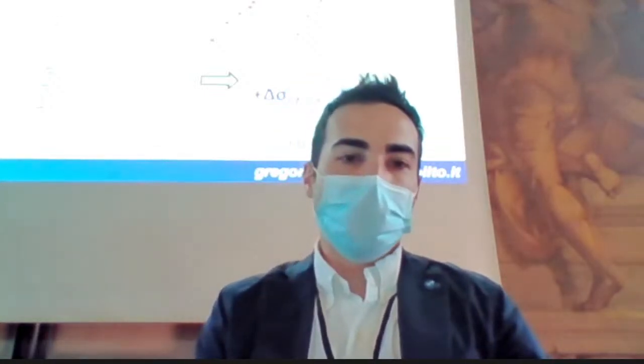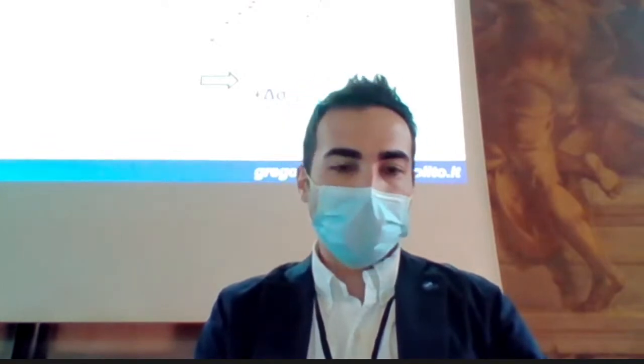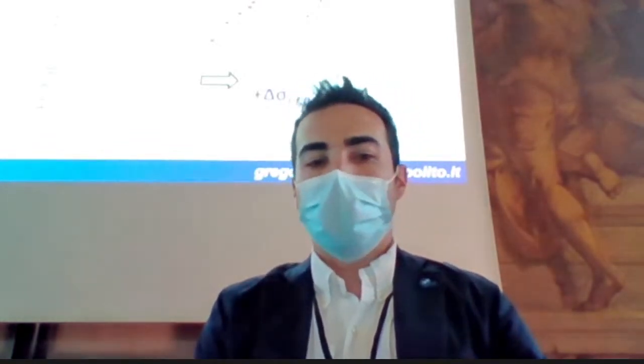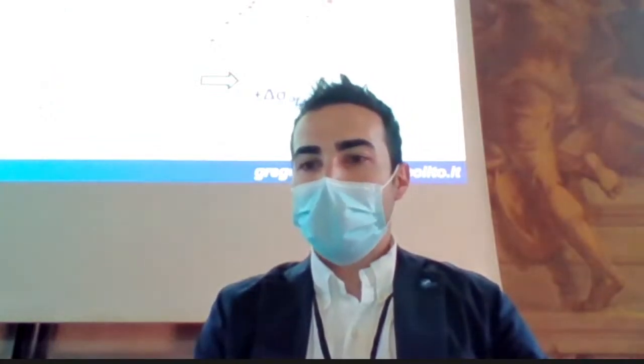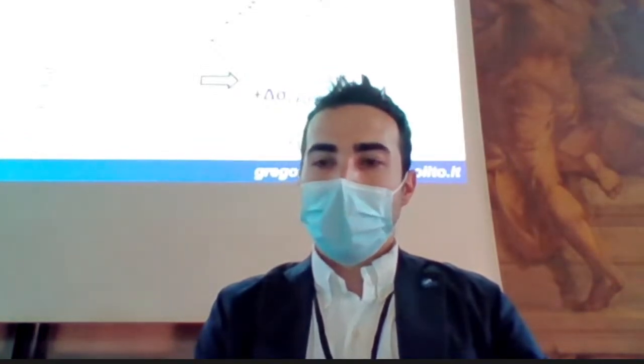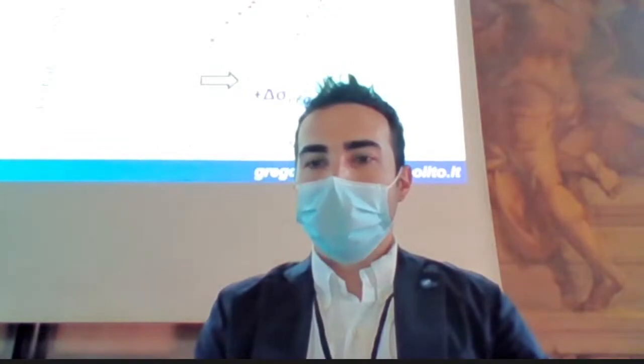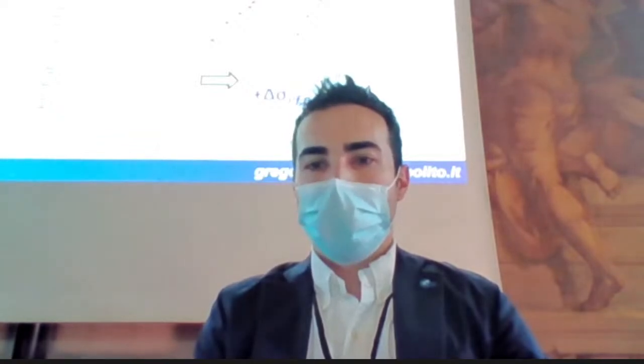Several properties of the coating were assessed, including transparency, wettability, barrier to water vapor, and adhesion to glass. The effectiveness of the coating was evaluated by comparing the Weibull distribution functions of the bending strength of coated glass and uncoated glass. As we can see from the graph, coated glass was the least affected by stress corrosion, as its Weibull distribution function was the most shifted towards higher stress values.